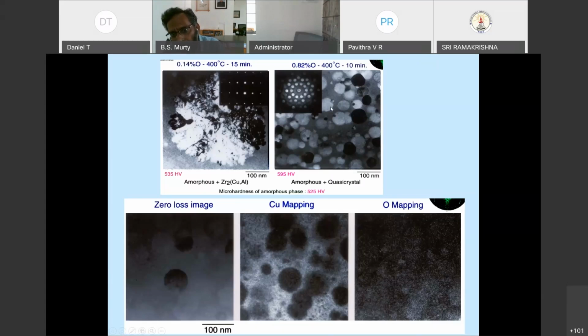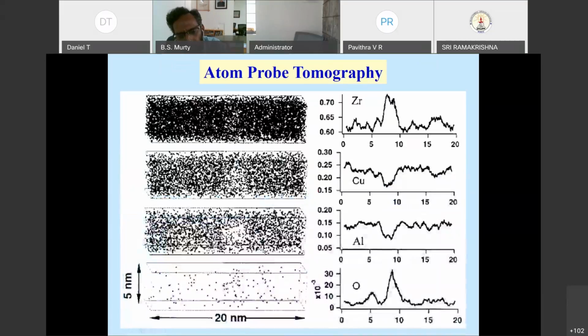Okay, and we wanted to see whether oxygen is getting concentrated into these particles, and the chemical spectroscopic techniques on the TEM were not able to give that. Something like an EDS cannot give you that. So then when we went to atom probe, we were able to see that there are small particles inside the sample. Here, each box that you see is containing one particular type of atoms.